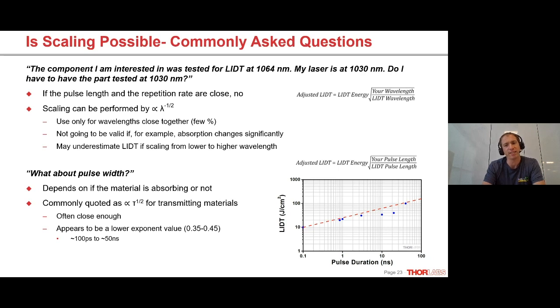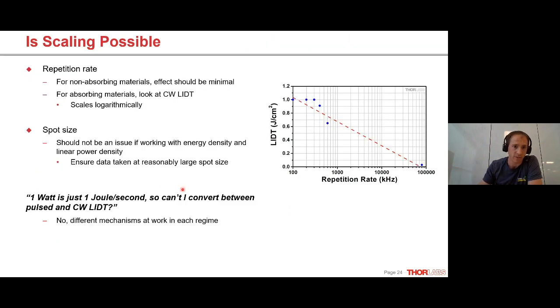I believe so. We tend to have all our parts tested under their use cases. So for example, a mirror that's intended to be used at 0 degrees, we test at 0 degrees. A dichroic mirror that's intended for 45 degree usage, we'll have that tested at 45 degrees. So I wouldn't expect to see too much variation between the tests and use case, but I also wouldn't expect too much to change, even if you tilt an optic to the quote unquote wrong angle. Because the spot size is going to change, but as I cover on this slide, that shouldn't be too much of an issue.